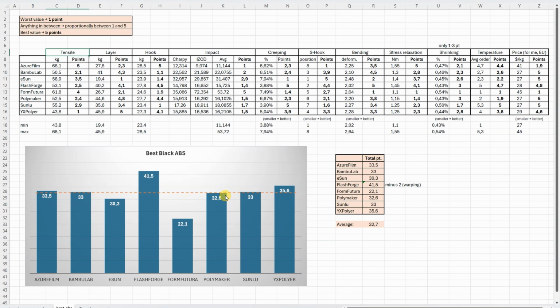So the average is approximately 32.7 points, and more or less all filaments around here. The FlashForge is the best, even though I took down 2 points because of that significant warping. This was the only filament where I had problems during the printing. And from this 8, in this case, the FormFutura is the worst. But as I mentioned, all others are more or less around the average value. But as I mentioned, none of them is perfect. For example, if you still need an impact resistance, in that case FormFutura is by far the best from this 8.